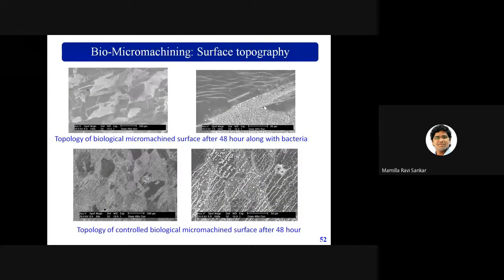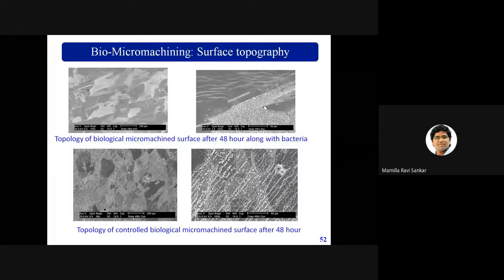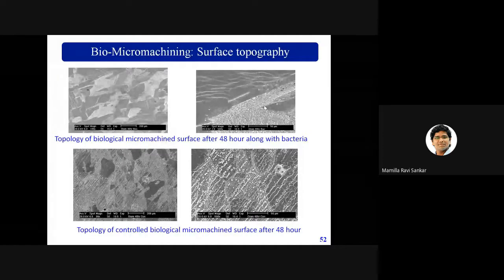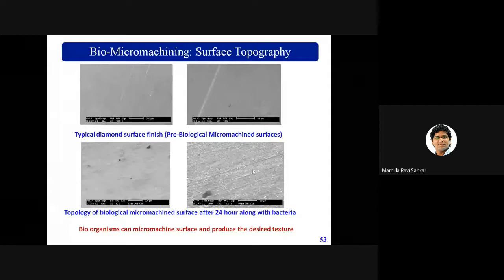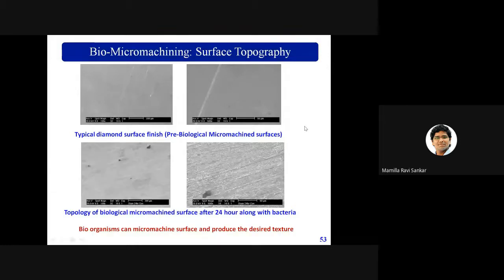We have now ventured into another area, which I will show in the upcoming slides. We also wanted to understand whether any metallurgically damaged layer is there. We have not found a metallurgically damaged layer, but we found that these surfaces have slightly higher roughness. They are very soft in nature, and you can even clean them with acetone and other things. Once you do the acetone cleaning, you can get very good surfaces. What I mean to say is that the surface topography is very good, as per the requirement.